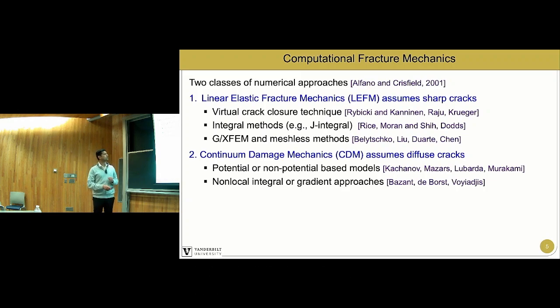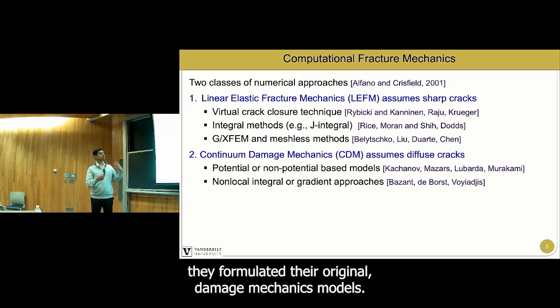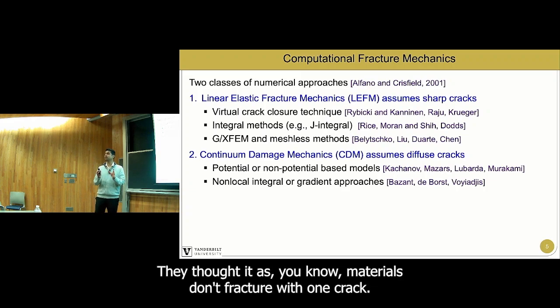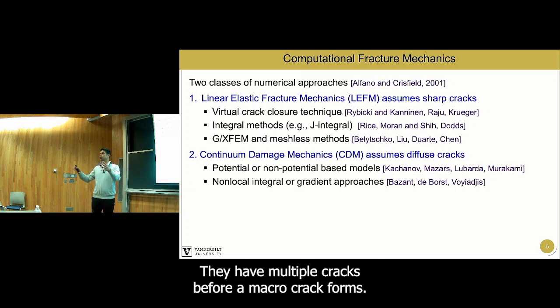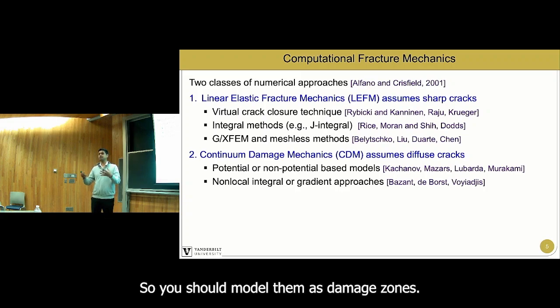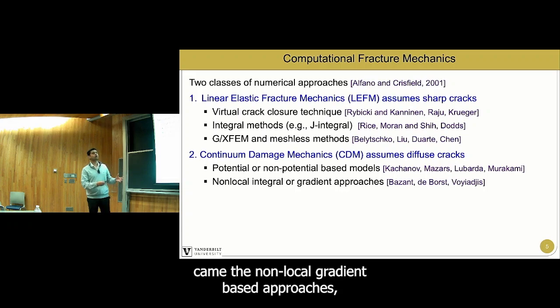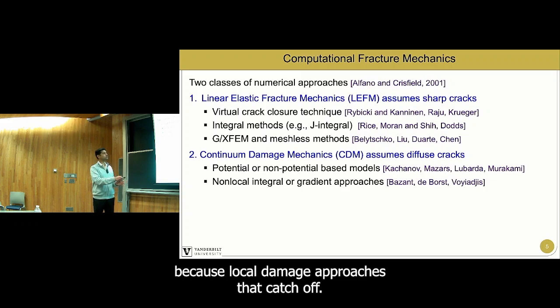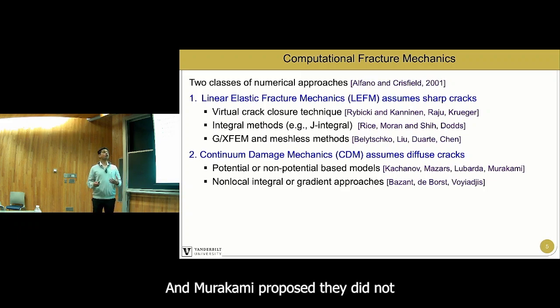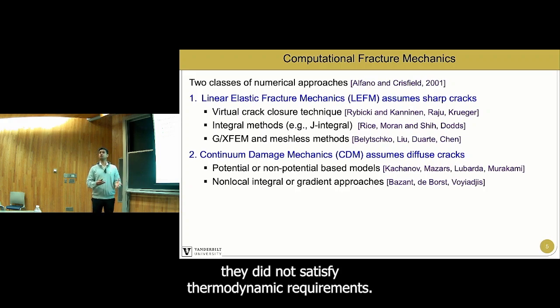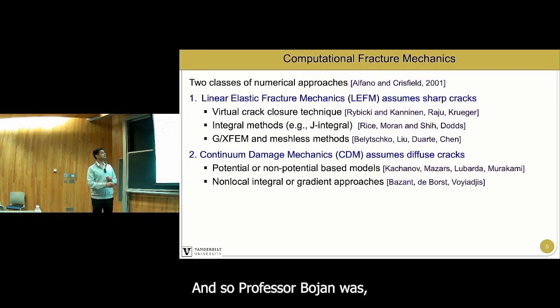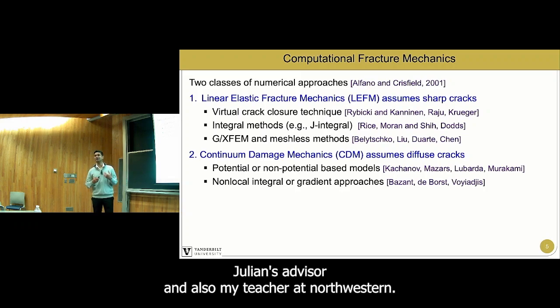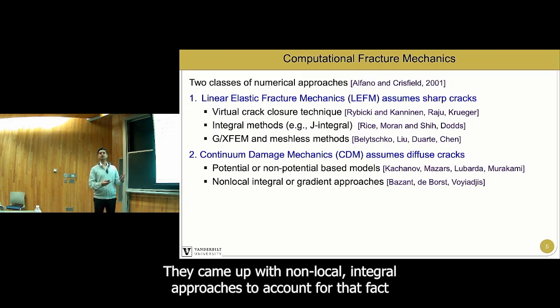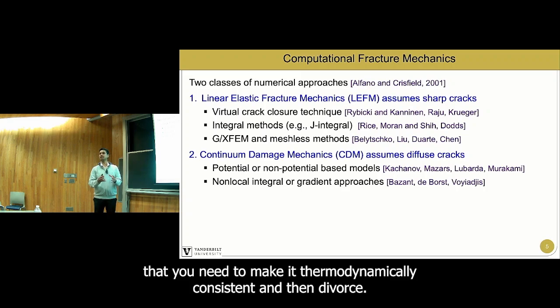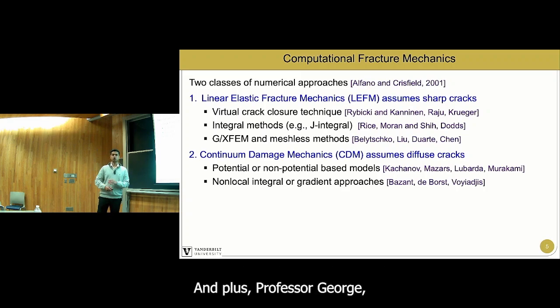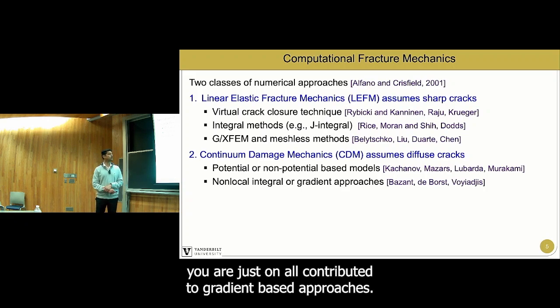diffused damage zone. When Kachanov and Mazars formulated their original damage mechanics models, they thought that materials don't fracture with one crack. They have multiple cracks before a macro crack forms, so you should model them as damage zones. And then came the non-local gradient-based approaches, because the local damage approaches that Kachanov and Murakami proposed did not satisfy thermodynamic requirements when you're doing modeling. So Professor Bazant, who's Jialiang's advisor and also my teacher at Northwestern, came up with non-local integral approaches to account for the fact that you need to make it thermodynamically consistent. And then de Borst and Professor George Voyiadjis and others contributed to gradient-based approaches.